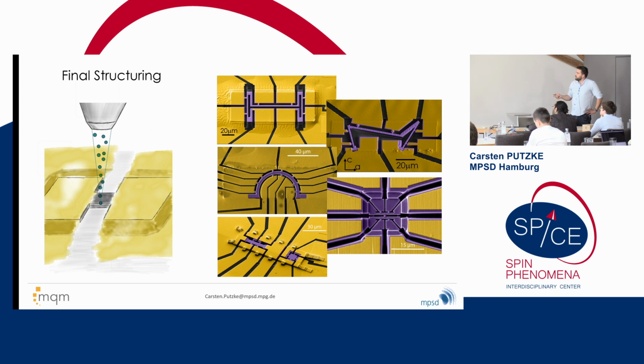You can look at this in arbitrary shapes. If you say the material should be isotropic, you might want to test this in any direction, not just the high symmetry directions. You can also look at non-local effects. So you can pass a current down here and compare the voltage on this side and this side. In the case where you have a surface transport-like phenomena, you would expect to see some voltage over here. But in the case where you don't have that, you would basically expect the voltage to be 0.